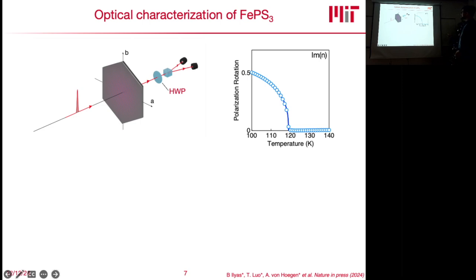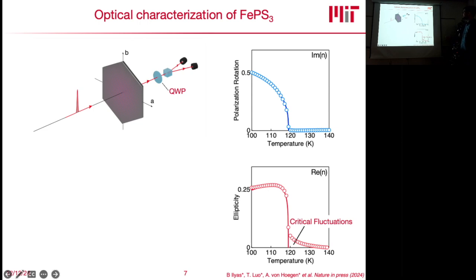And you can see that above the critical temperature of this material, there's no polarization rotation. However, once it goes into its magnetic state, this material shows a very, very strong polarization rotation, which is due to the anisotropy of this material due to these zigzag chains. We can also probe this with a quarter-wave plate, by replacing our half-wave plate with a quarter-wave plate, we're not measuring the polarization rotation anymore, we're measuring the ellipticity. So this is another polarization property of your light. And again here, you can see this very stark contrast between above and below the critical temperature. So indeed, with these two characteristic features, we are able to probe the magnetic state in this material.